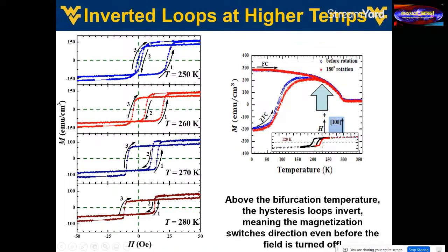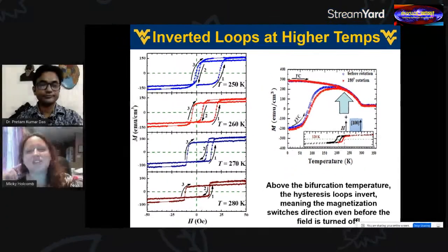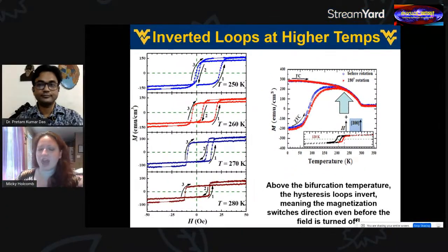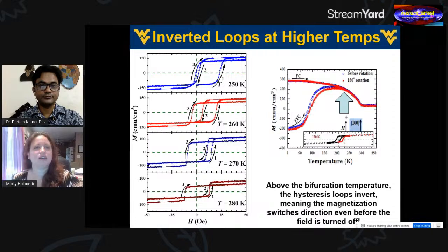Here, I'm turning down the field, and when the field gets small enough, it actually reverses direction. So just turning down the field, if you're at high enough temperature, so around room temperature, now we get this switch in magnetization. This is where this gets really interesting when you start thinking about applications, because now you have a magnetization that can be switched in direction with merely just adjusting very slightly the magnetic field.